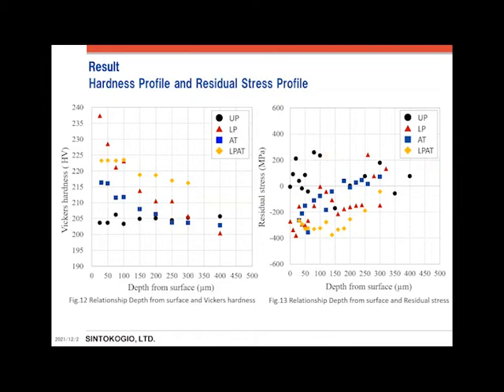The right figure shows the relationship between residual stress and the depth from surface. The residual stress measurement was not possible for the alumite layer, so AT and LPAT were measured from deeper than the eroded layer. Compressive residual stress occurred up to about 300 micrometer by the laser peening. Compressive residual stress was not released by the alumite treatment in LPAT condition.